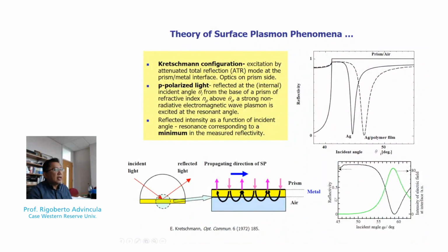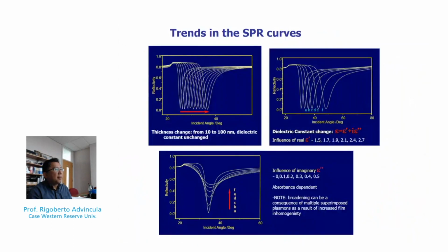Now, the other thing is the graph below shows that as you have this shift or dip in the reflectivity curve, one can also monitor the intensity of the scattered light by putting a detector in front of the surface. So this scattered light in many instances is very useful as well for development of sensing or investigating phenomena. Now, as a way of modeling, one can change the thickness of the film.